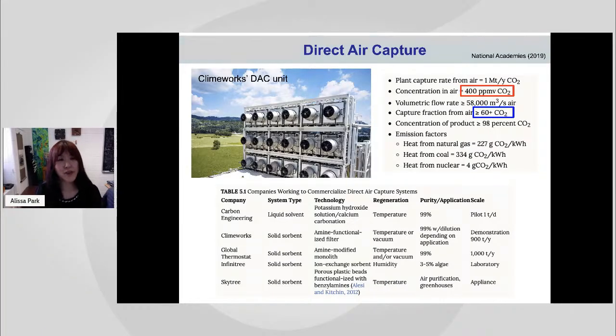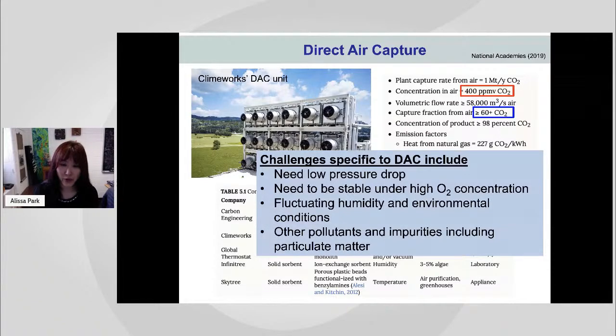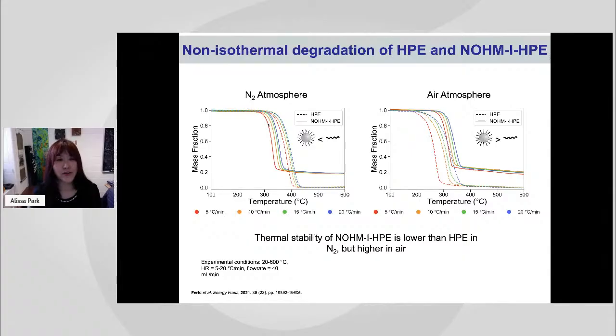Other challenges specific to direct air capture are that we need very low pressure drop because we need to move so much air through this unit. And it has to be very stable under high oxygen concentration because air has 21% oxygen. Also, you have to work with fluctuating environmental conditions, for example, rainy days versus very dry days, and so on. So with these challenges, people started to look into how to move air very well, like the direct air capture unit shown here, or how to develop CO2 capture materials specific to these challenges. So the first thing we looked at was oxidative thermal stability. Can we leave this material outside, do the temperature swing, and still be very stable?